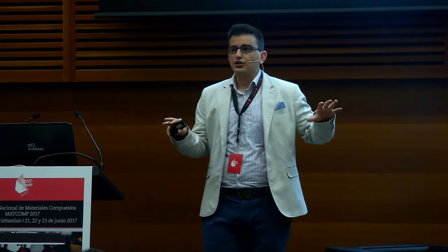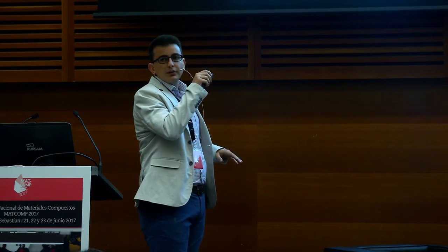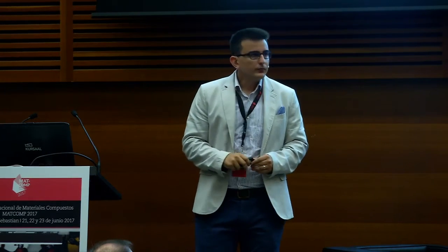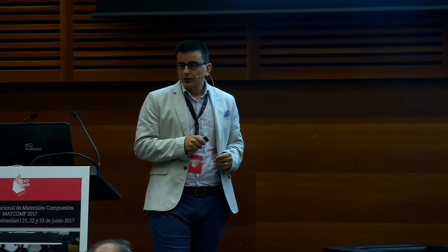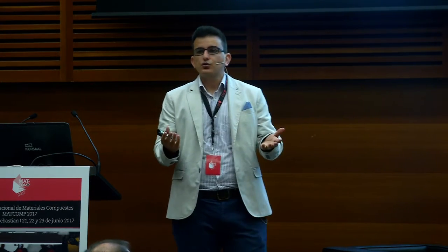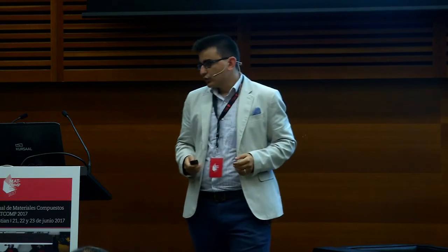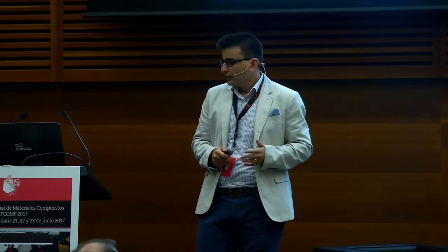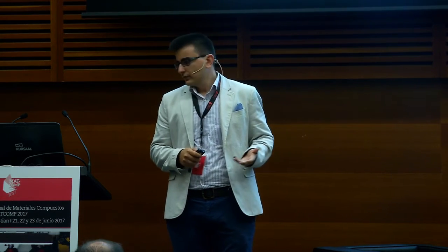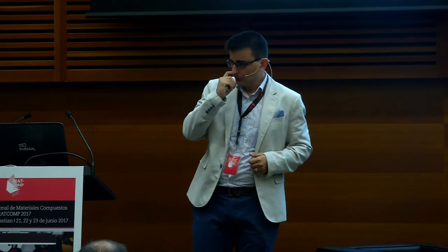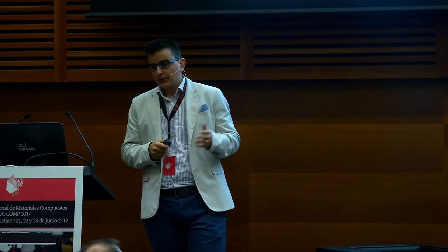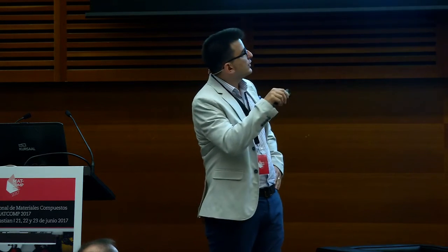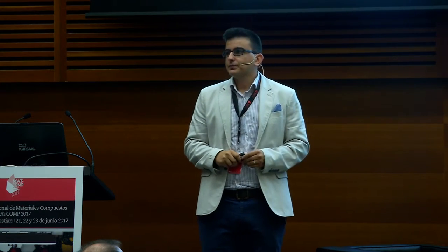Let's have a brief look at the temperature and degree of cure evolutions from the optimization problem. We have temperature here and degree of cure and the axial distance during the pultrusion process. So in the reference or initial case, we have 3 heaters. So the company was using actually 3 heaters with a die length of 1 meter. And we proposed, with the same pulling speed, to use 2 heaters with a much shorter die. And this provides more or less the same degree of cure evolution if we compare it with the initial case.